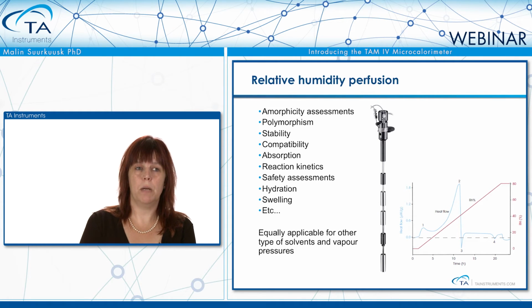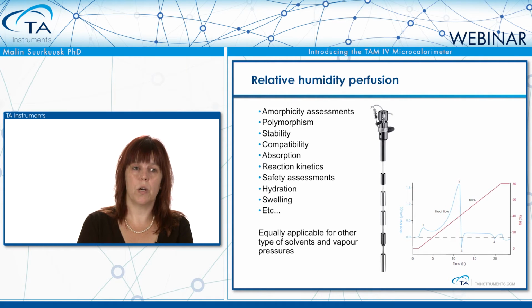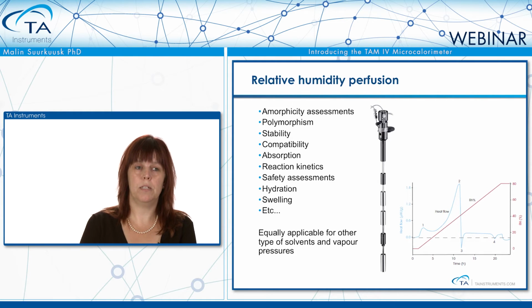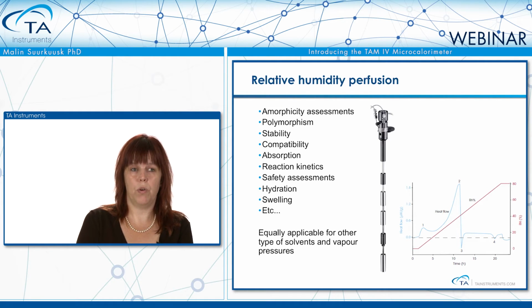In the humidifying chamber, the gas flow, nitrogen mostly, is humidified to 100% relative humidity. And then by controlling the two gas flows, the dry and the wet gas going in, we can regulate the relative humidity over the sample in the reaction vessel. The example shows again a lactose sample with amorphous region, where the red curve is a constant linear ramp of increasing relative humidity over the sample, and the blue line is the heat flow from the sample.